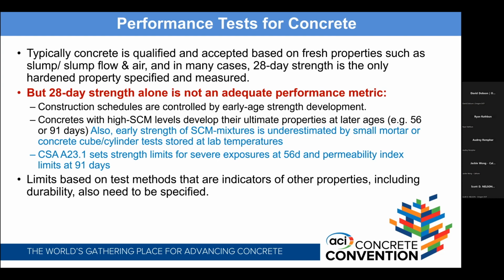Concretes with high SCM levels typically develop their ultimate properties at later ages. And so in the Canadian standard, we set limits at 56 and 91 days, as opposed to the 28 days when there's durability requirements.